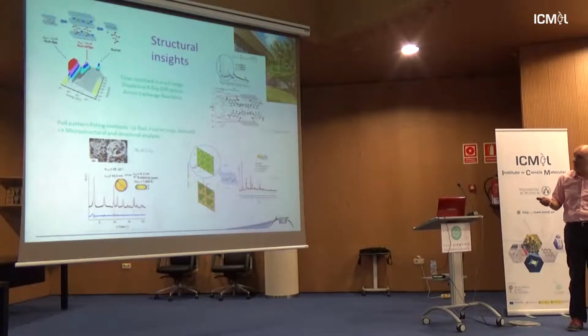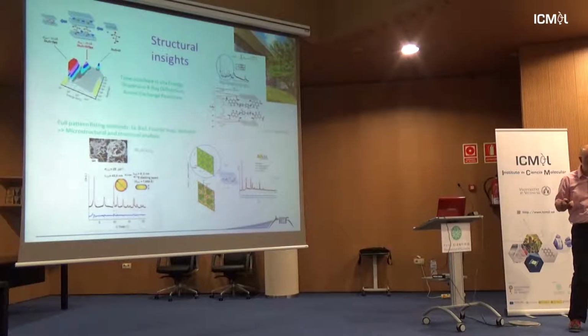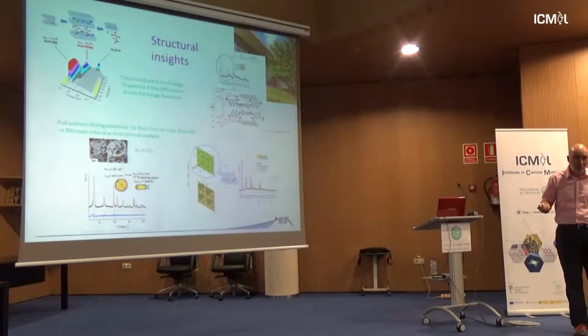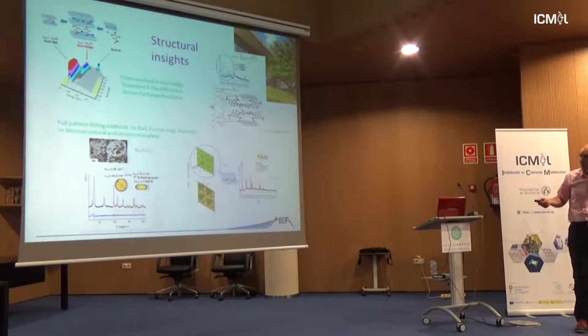In terms of characterization, it's very important, of course, to characterize our LDH samples as well as possible, and for that we use time-resolved in-situ energy dispersive X-ray diffraction, so you use synchrotron, and in this case it's really a spectrum, an X-ray spectrum, because it's energy dependent. It's a complete white beam that you are putting on your materials. It's not just copper radiation, so you get a spectrum. Otherwise, it would be a diagram, of course.